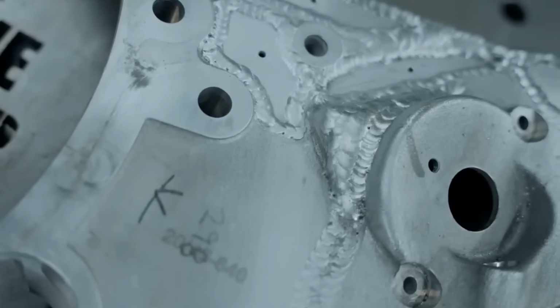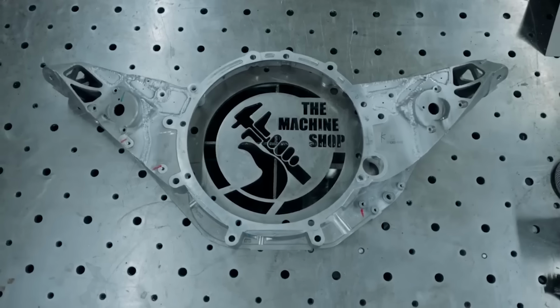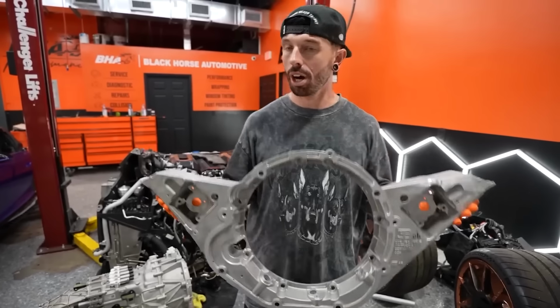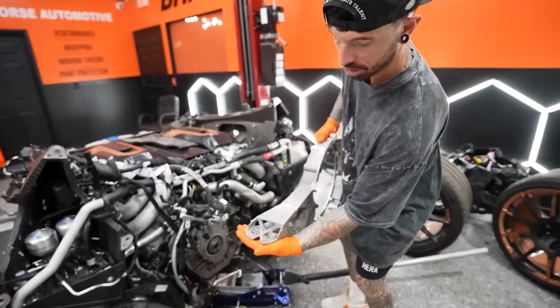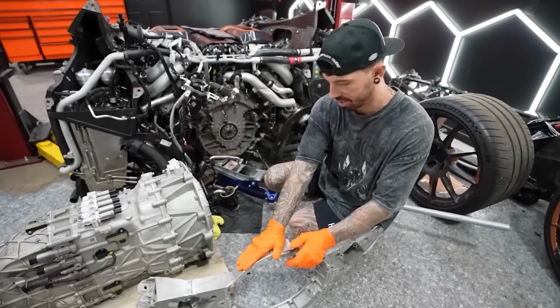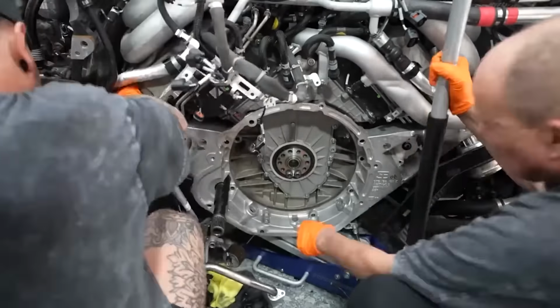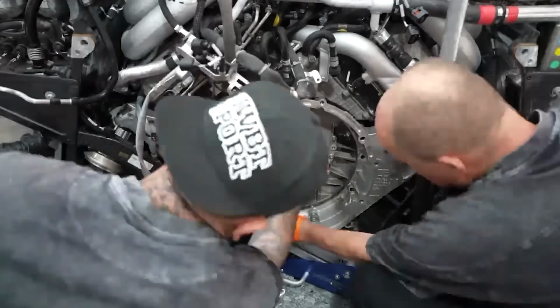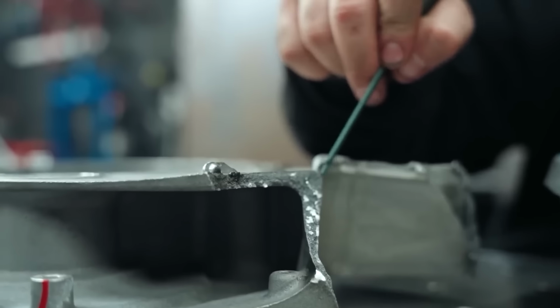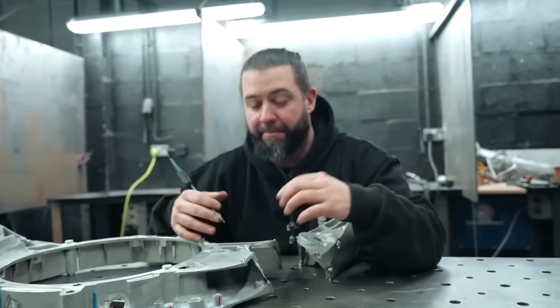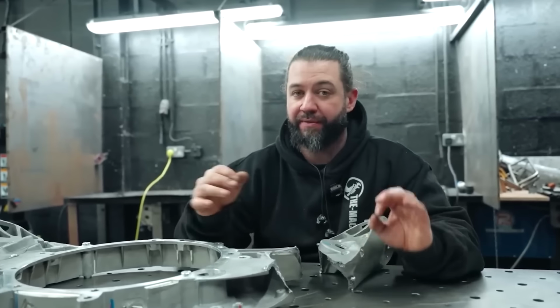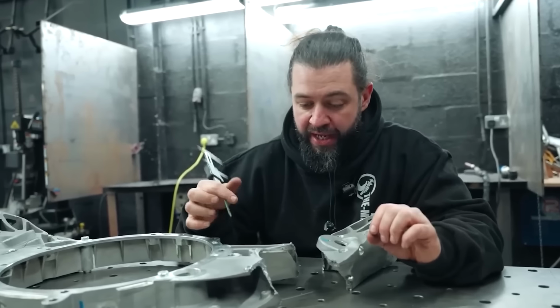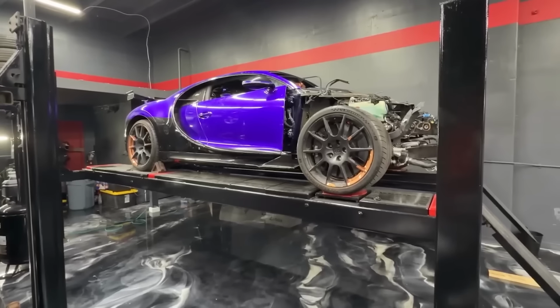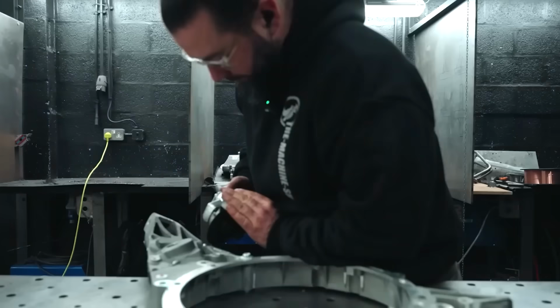Some sections of the aluminum show a dull, cast texture that's been disturbed and hammered looking. Bob's read on that? After the crash, the car was driven. Briefly, but enough. The engine vibrating against a compromised mount repeatedly stressed the same fracture point until the cracks spread further. The part didn't just break once. It was being broken, slowly, every time the engine fired. This isn't a simple fix. But Bob doesn't do simple.